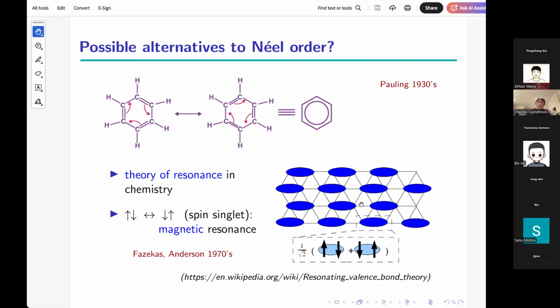Okay, thank you. Yeah. Then there is one subtlety that I'll mention in the next slide. One thing to notice here is that if you do this recipe of forming singlets between nearest neighbor pairs of electrons, the singlet is perfectly antiferromagnetic within itself, represented here by these thick blue bonds, but the thin bonds, the nearest neighbors across singlets, 50% are ferromagnetic and 50% are antiferromagnetic. So you have a finite density loss in terms of antiferromagnetic energy.